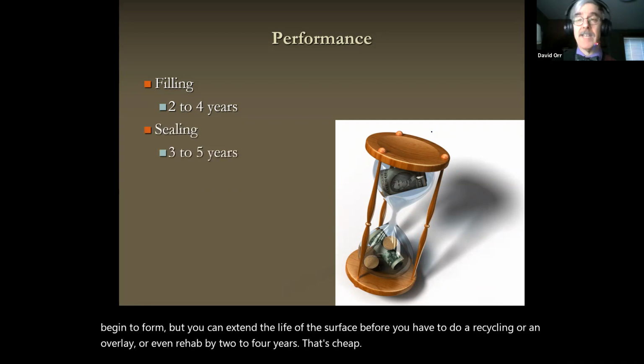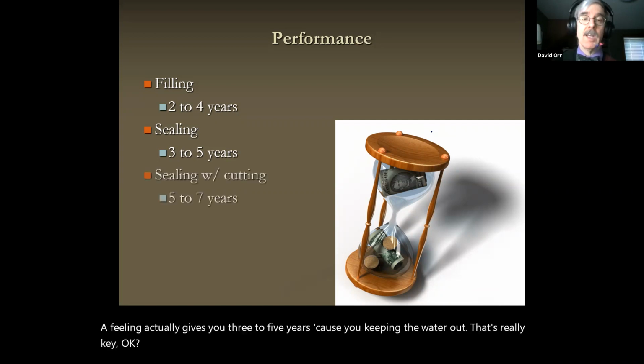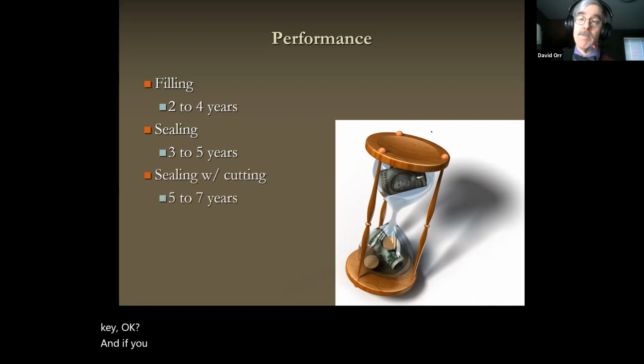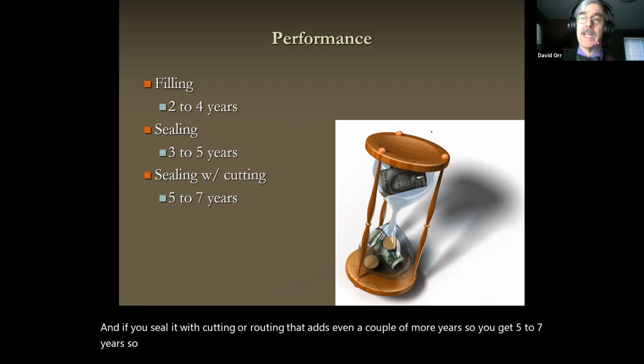Sealing actually gives you 3 to 5 years because you're keeping the water out. That's really key. Okay. And if you seal it with cutting or routing, that actually adds even a couple more years. So you get 5 to 7 years. So it's definitely worth looking at sealing your cracks. If you don't have it in your toolkit, you need to add it.